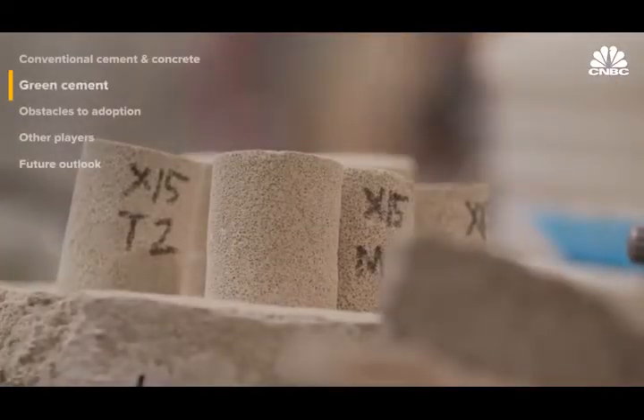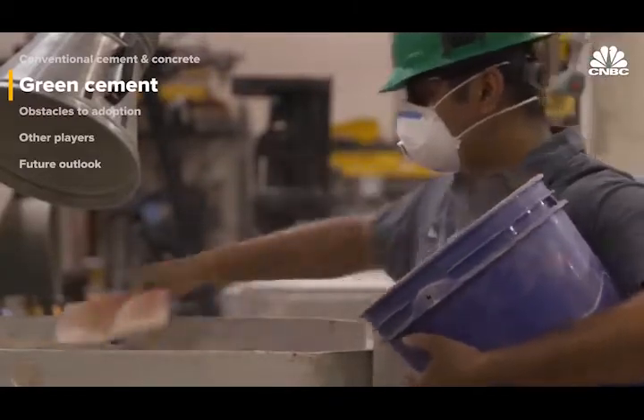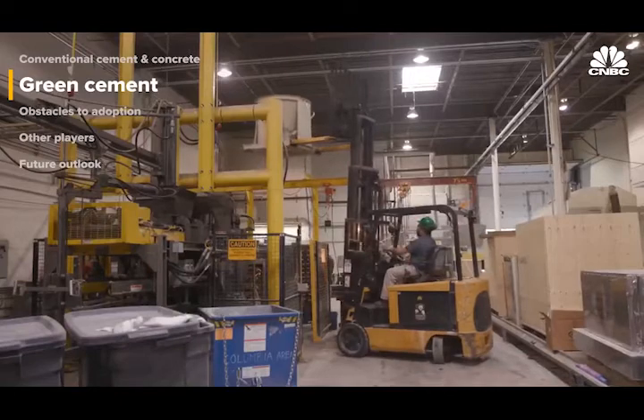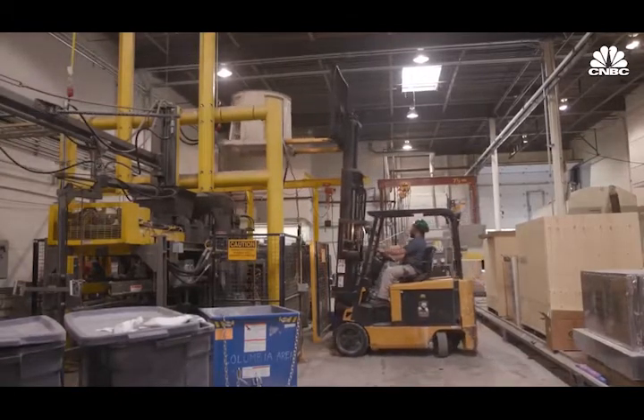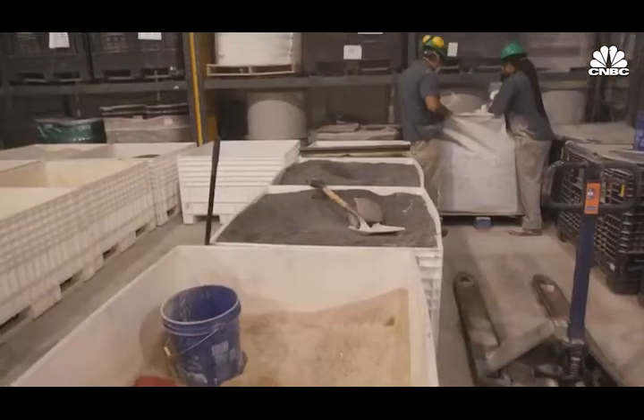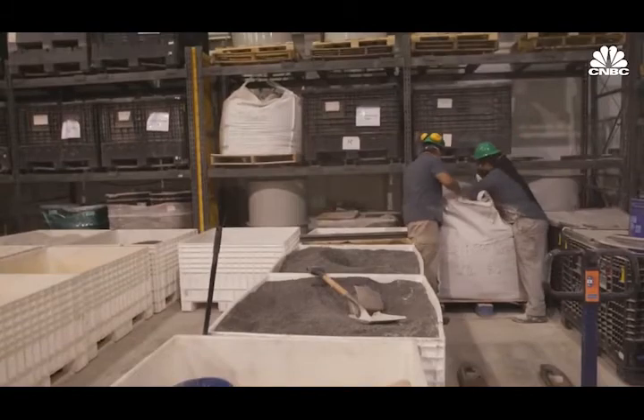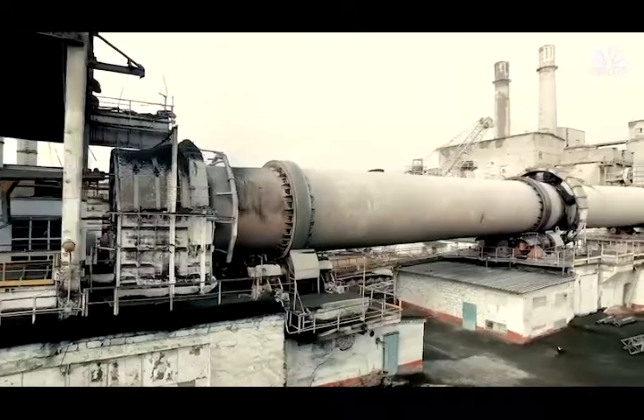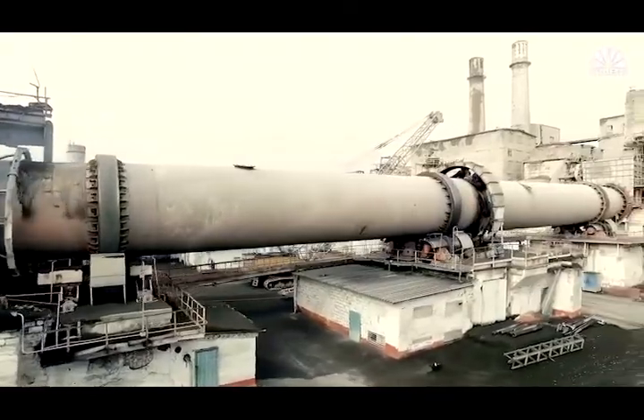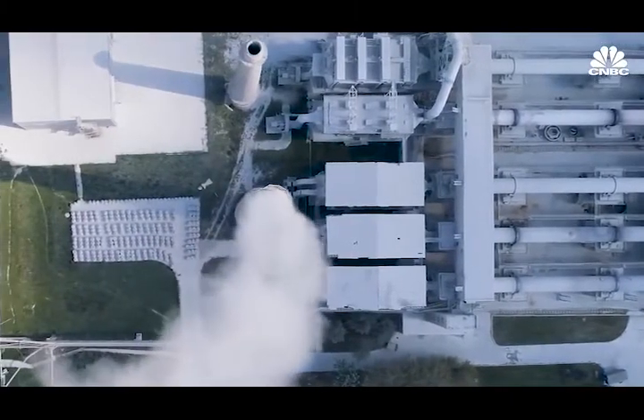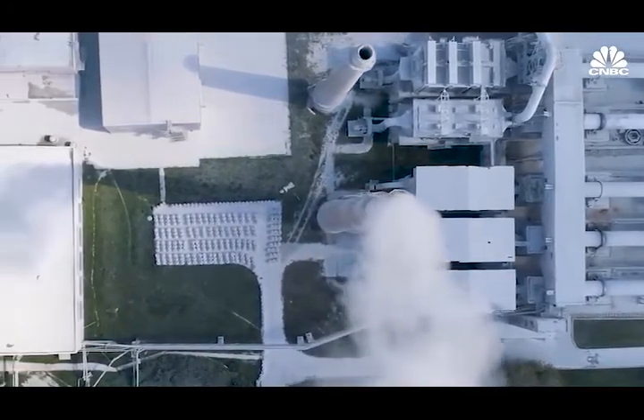In order to reduce the carbon footprint of its cement, Solidia Technologies had to slightly alter the chemistry of the mixture. But the process and equipment needed remains largely unchanged. In order to make Portland cement, you use limestone and sand, you mix it about 2/3, 1/3, and you put it into a kiln that reacts at about 1500 degrees Celsius, so really hot. We take exactly the same raw materials, but we change the recipe a little bit. We mix it about 50-50, and that reaction happens at a much lower temperature, about 1200 degrees Celsius. Now what that means to the cement company is instead of emitting 1 ton of CO2 for every ton of cement, they emit about 40% less than that, and they use 30% less energy to make that same amount of cement. They also get more cement with the same amount of raw materials.